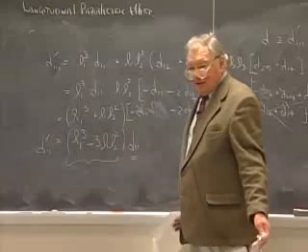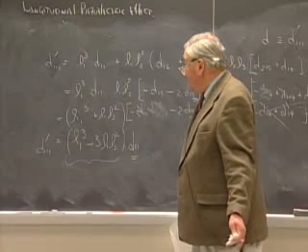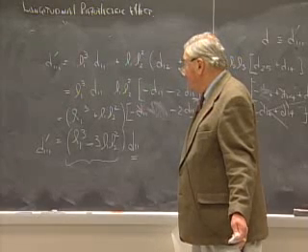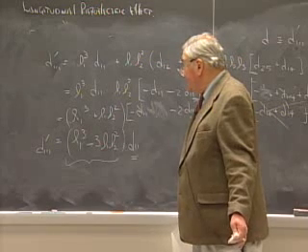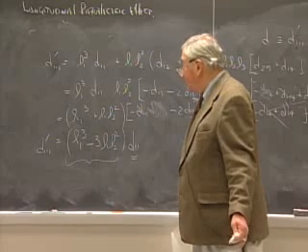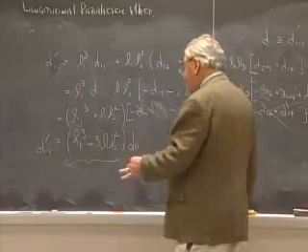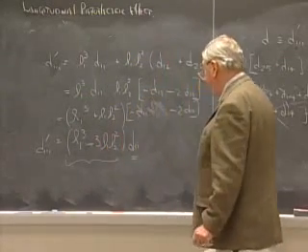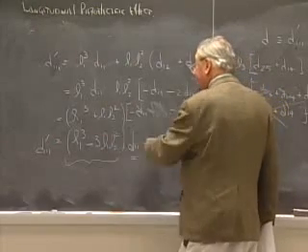This says that the shape of this surface is independent essentially of the property, any property that relates D11 prime to a uniaxial stimulus, sigma 11, and you measure a vector component in the same direction, is always going to have this universal surface. And it involves just a geometric term and then one modulus that changes the magnitude of the longitudinal piezoelectric modulus but does not change the asymmetry.